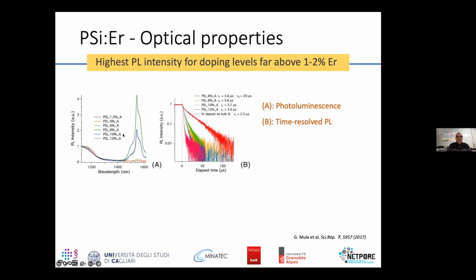If you look at the time resolved photoluminescence, you can see that where you have the highest luminescence peak, you have two different time constants that are indicating that you have two different erbium compounds present in your structure. While when you go to higher content again, you have again a single transient. So this means that in this particular condition, when you have the highest peak, you also have the presence of two different compounds that can be identified as erbium silicate toward the silicon interface, and erbium oxide in the inner part and on the surface of the sample.